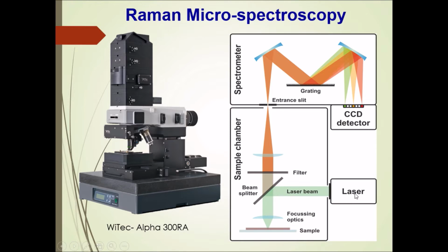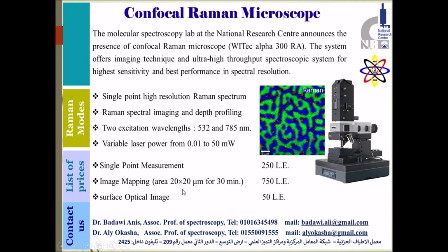In this Raman microscope, we can use a laser as the excitation source, and then using some focusing optics, we can focus the laser beam on a specific point on the surface of our sample. The Raman signal can go directly, using fiber optics, to the spectrograph, using different kinds of gratings, so we can distinguish between several Raman peaks. Then we can send this spectrum to the CCD detector. Using Raman software, we can distinguish between several peaks and several contributions from our sample.